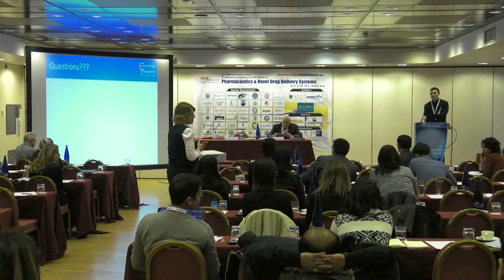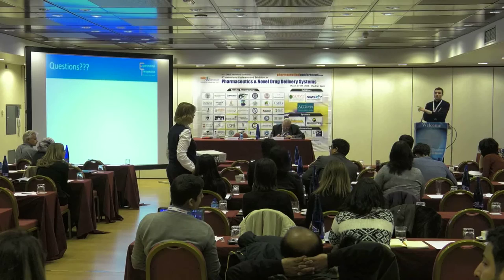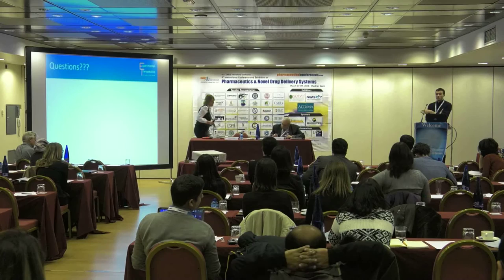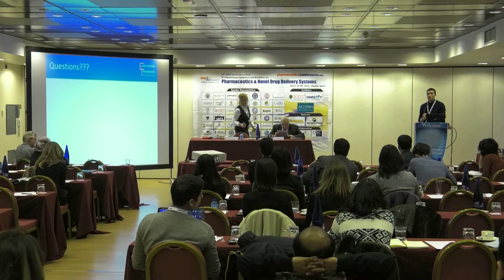Question from audience: Have you thought about using a degradable PEG linker, so that you have the PEG on the particle while you need it, and then in the endosome or somewhere in the cell it degrades? Response: Yes, that's actually the next step. We're looking at using an MMP-cleavable sequence, so that once the tumour is reached — particularly relevant for prostate cancer, which has up-regulated MMPs — it would cleave the PEG and improve the transfection capability of the nanoparticle. It also improves specificity.